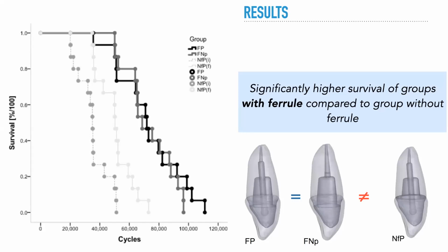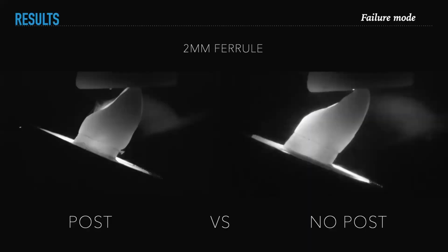So ferrule was the most important factor in the survival of the groups. And we didn't have a difference between the ferrule groups with post or without post. So the only difference was in the groups without ferrule. But a further problem with the fiber post was revealed with the higher rate of catastrophic failure.